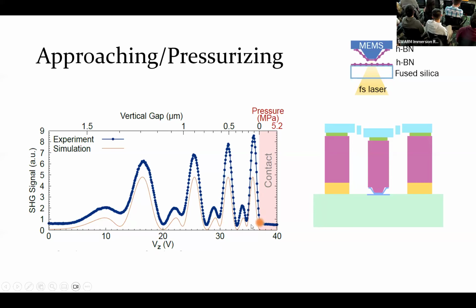This is really a characteristic of the mini optical cavity that is formed between the 2 layers. So it's like a Fabry-Perot cavity as we are moving the 2 layers closer and farther apart. And the period between these oscillations actually corresponds exactly to half of the wavelength of the laser we use to excite this system. So that would be 390 nanometers. So we can use this to precisely calibrate the MEMS device, because now we can convert the voltage we apply onto the electrostatic actuator to the gap between the 2 sheets of 2D materials.